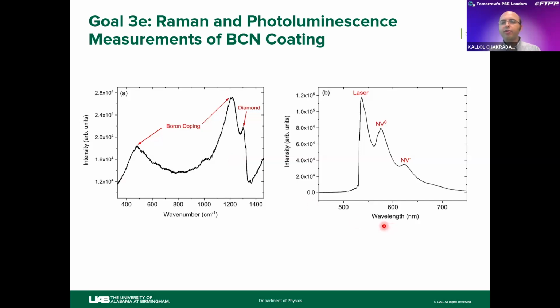We also did photoluminescence spectra, and according to the photoluminescence, we also have a nitrogen center. So in our lattice we have both boron and nitrogen doping—this confirms it is the BCN coating.